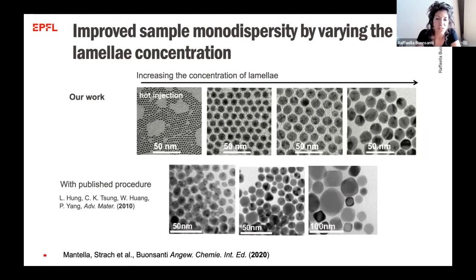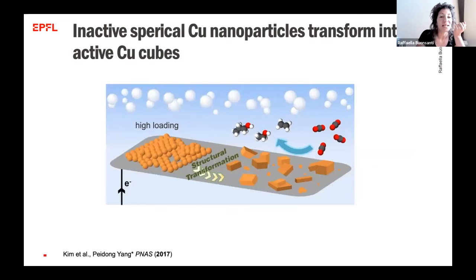And why is monodispersity important? Well, it turned out this is important if we want to study how these particles might change also during electrochemistry. We were basically intrigued by a work reported in the literature where it was demonstrated that these small copper particles at a specific loading evolve into cubes. And I did not specify before, but these small copper particles with a large fraction of under-coordinated sites are somehow more active for hydrogen. So here the authors demonstrated that they evolve into cubes, and we got intrigued by the structural transformation because we wanted to understand how this actually happened.